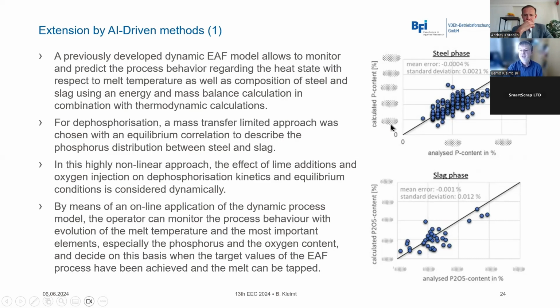So you can see here that in the steel phase, as well as in the slag phase, the model allows to calculate the phosphorus concentration at the end of the EAF treatment with a very good accuracy. And this can also be used for monitoring the process behavior, but also to determine the endpoint of the process when the target values of the EAF process have been achieved and the melt can be tapped.